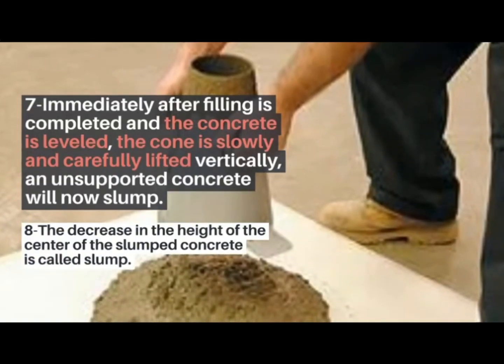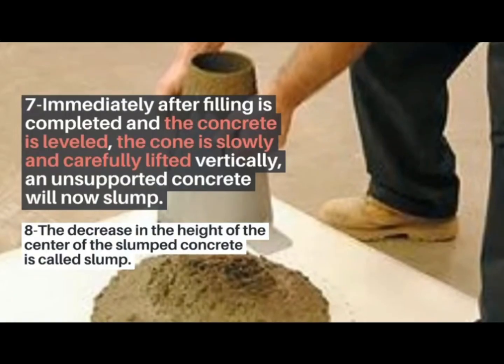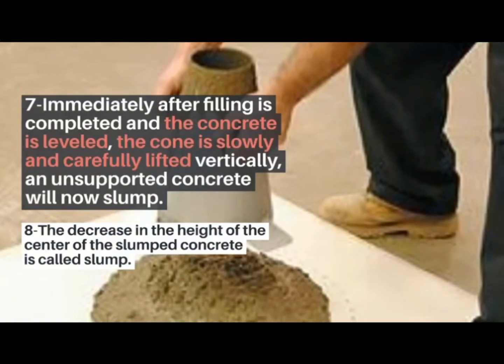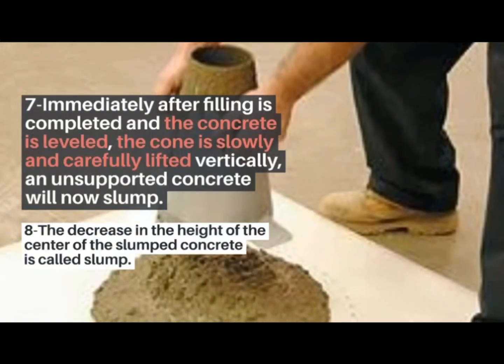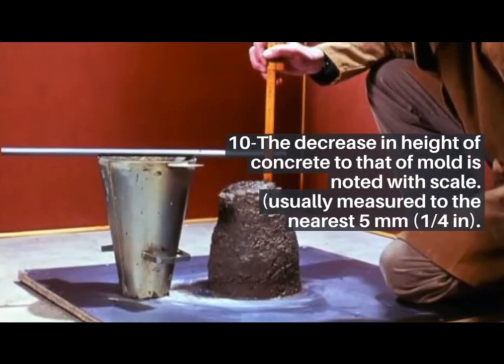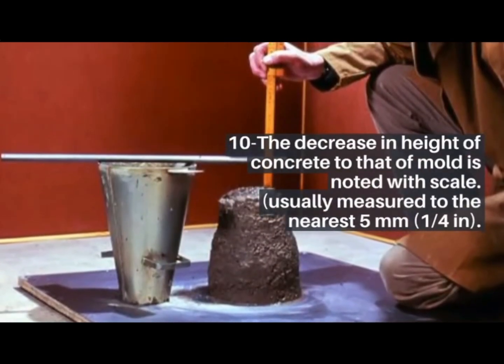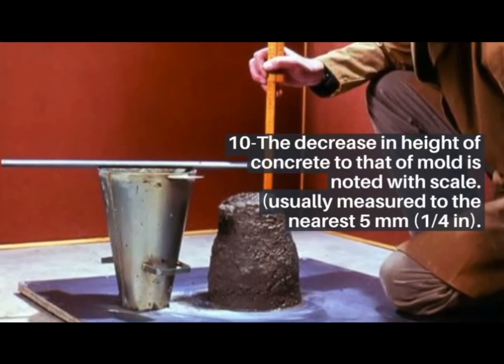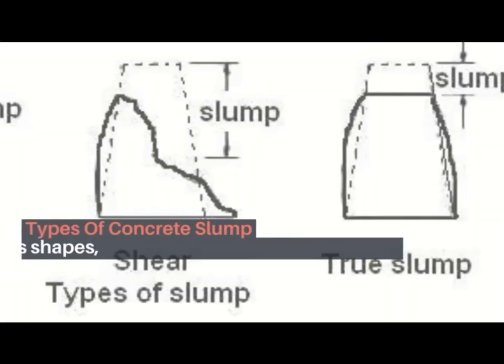7. Immediately after filling is completed and the concrete is leveled, the cone is slowly and carefully lifted vertically, and the unsupported concrete will now slump. 8. The decrease in the height of the center of the slumped concrete is called slump. 10. The decrease in height of concrete to that of the mold is noted with a scale, usually measured to the nearest 5 mm (1/4 in).